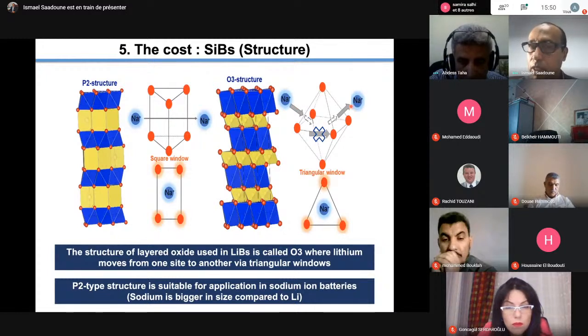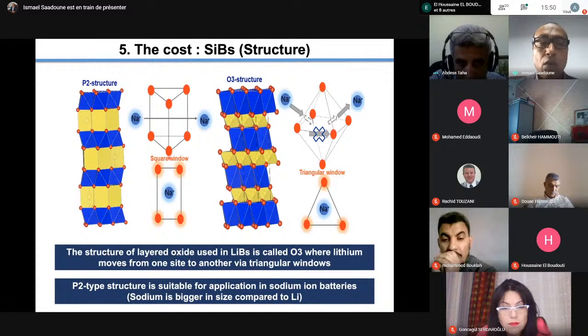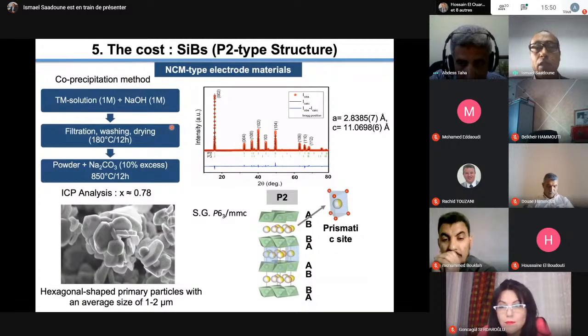So the approach now is to prepare sodium layered oxide, but with a structure where sodium is in a prismatic site. Because if sodium is in a prismatic site, diffusion can occur through a rectangular or square window, making it much easier to achieve high diffusion, high charge rate, fast charging, or fast discharge. So what we do is go directly to the P2-type structure and prepare a new material, NMC.